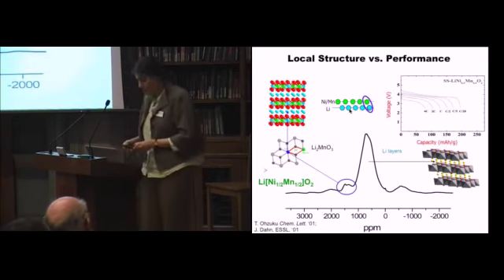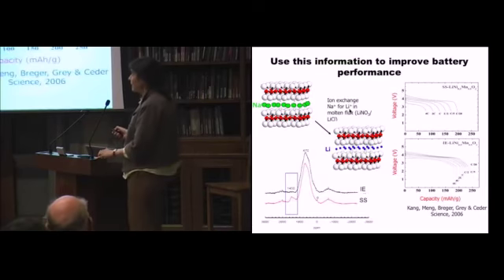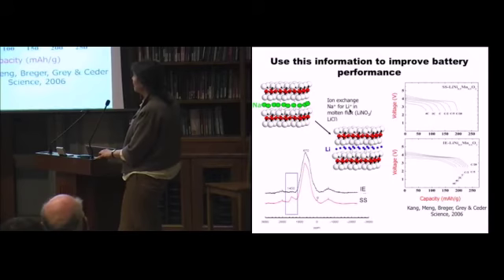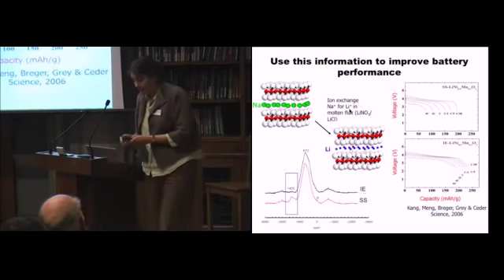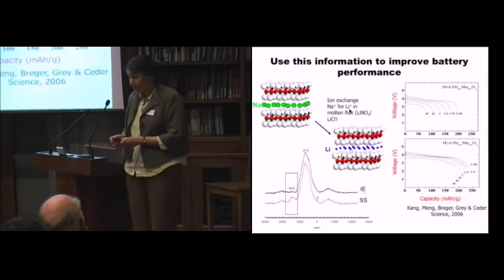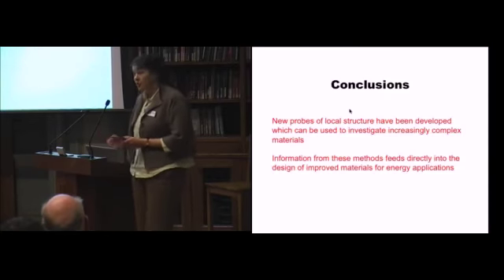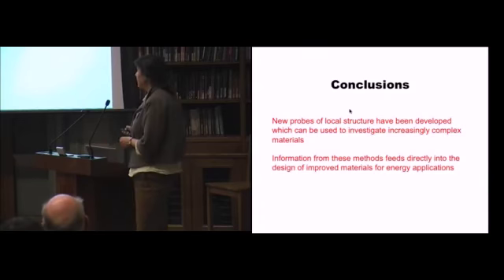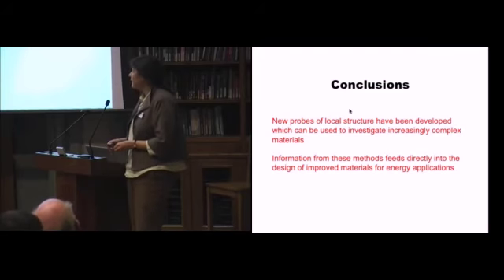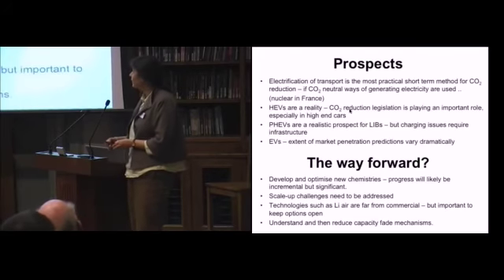Once we'd realized that, we then thought about how to make an improved material. You can make the material with sodium, you can replace the sodium by lithium, and when you do that, you get a tremendous increase in the performance of the material, and you have a material that you might be able to use for a hybrid electric vehicle. So with that, I hope I've shown you that we're able to interrogate or look at the local structure with new probes of local structure, and this information feeds directly into the design of improved materials.